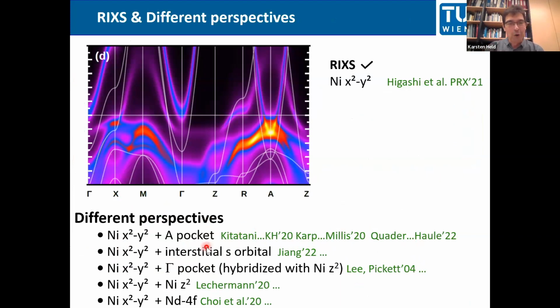But okay, you know superconductivity, and there's a lot of fight of mechanism, and here's even a fight of what is the most fundamental or relevant model, and many different groups have arrived at different key ingredients that they think is important besides this minimal description. For example, at the beginning, there was a lot of excitement that you have a superconductor with 4f electrons. So some people thought that's important, but lanthanum nickelate has no 4f electrons, and so it doesn't seem to be so relevant. Then there is a z-squared orbital, which I mentioned before. So in other calculations, for example, in DFT plus DMFT, it crosses the Fermi level, and then from that kind of calculation, you conclude it has to be included in the minimal model as well.